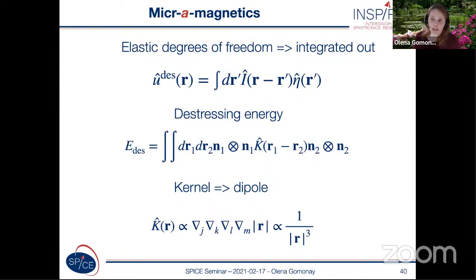We can reformulate the problem of antiferromagnetic structure in terms of the Néel vector by introducing this destressing energy, which involves implicitly the magnetoelastic interaction. We find that the expressions for the destressing energy are more complicated compared to the ferromagnetic case. They involve 4 components of the antiferromagnetic vector instead of 2 for a ferromagnet, and they involve tensorial Green functions and so on. But this is hard, and this is nice, because it opens a lot of problems for young people, and I would hope the progress does not stop with my talk.